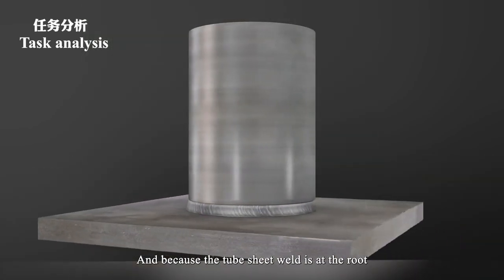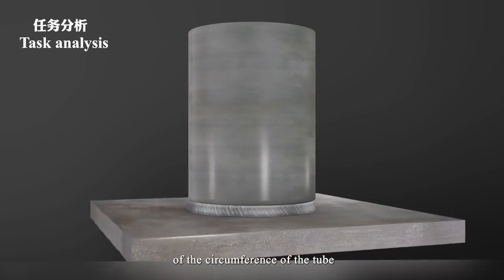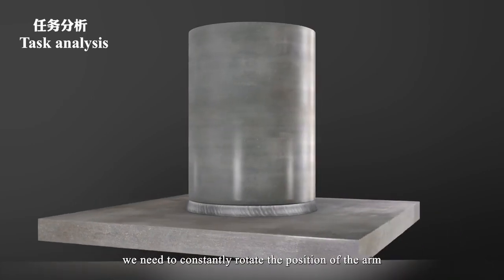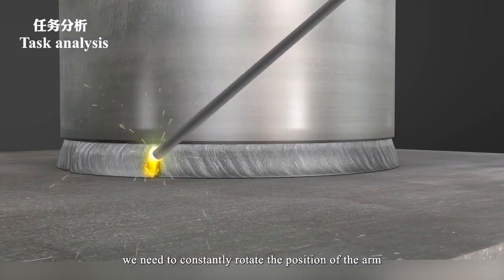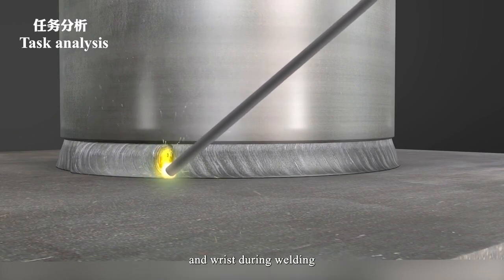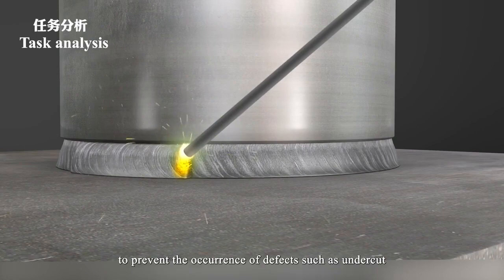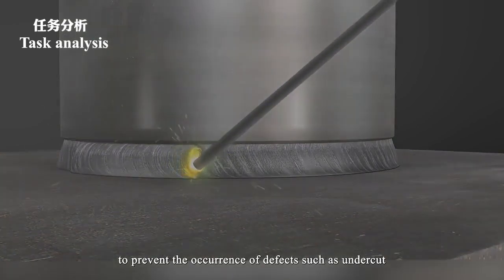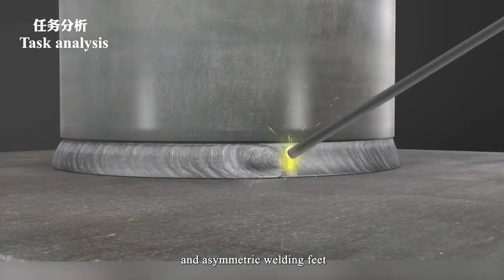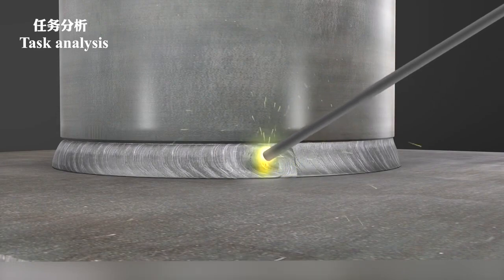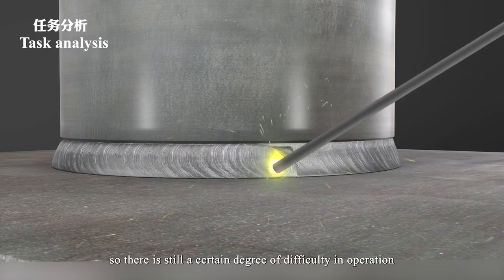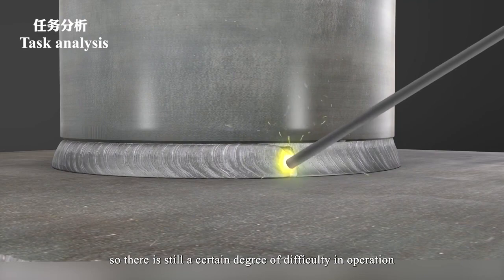And because the tube sheet weld is at the root of the circumference of the tube, we need to constantly rotate the position of the arm and the wrist during welding to prevent the occurrence of defects such as undercut and asymmetric weld fit. So there is still a certain degree of difficulty in operation.